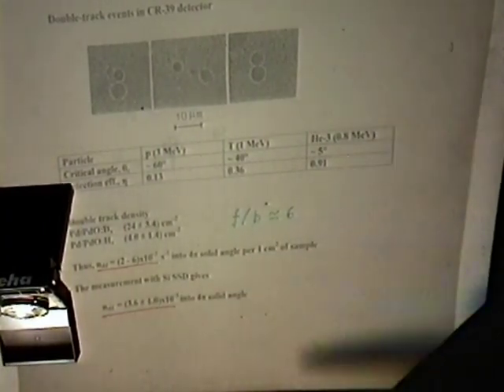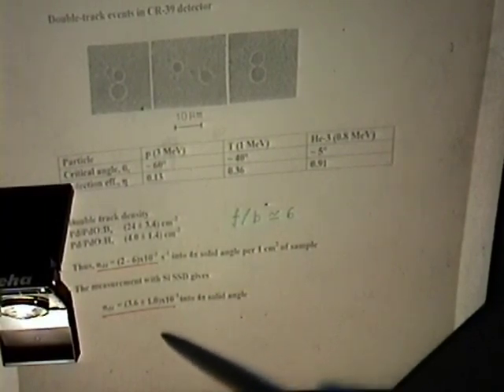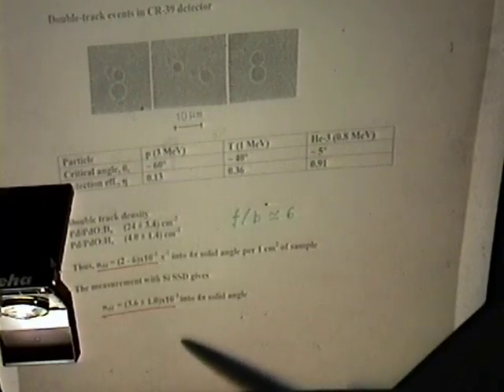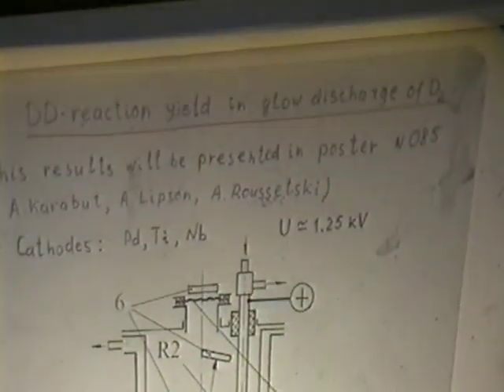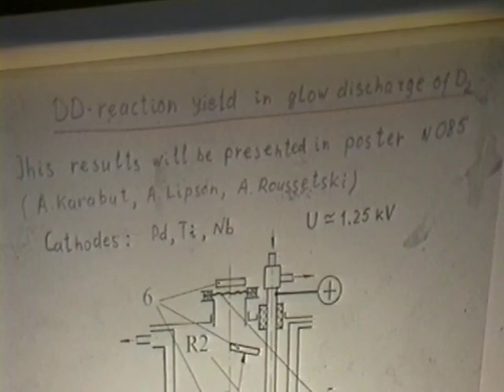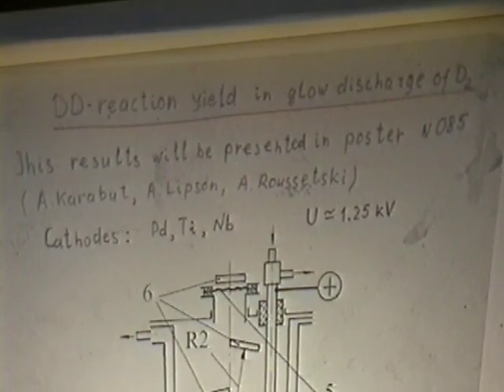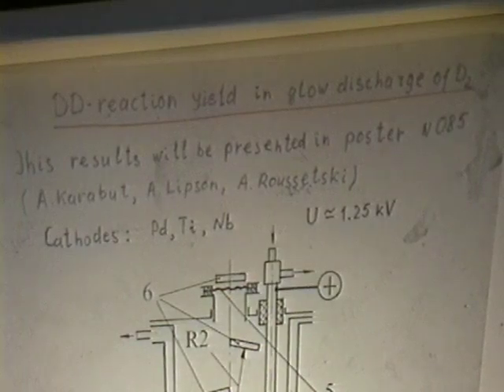The measurement with the same samples carried out by silicon surface barrier detector gives the value 3.6 plus minus 1 times 10 to the -3 into 4π solid angle. The DD-reaction yield was also estimated in the experiment in glow discharge of D2. These results will be presented in the poster number 085.